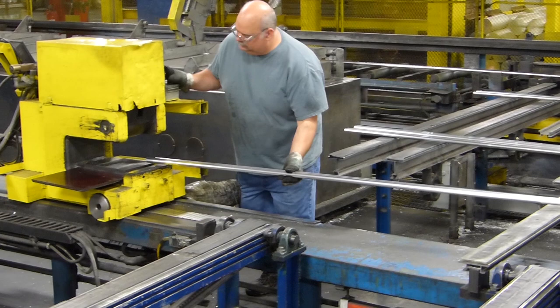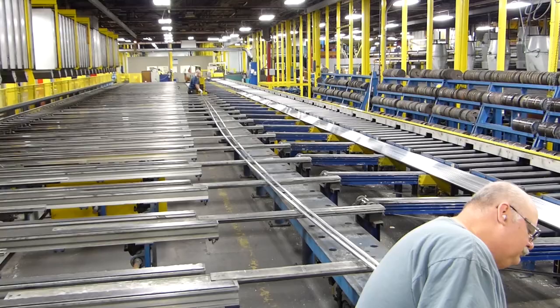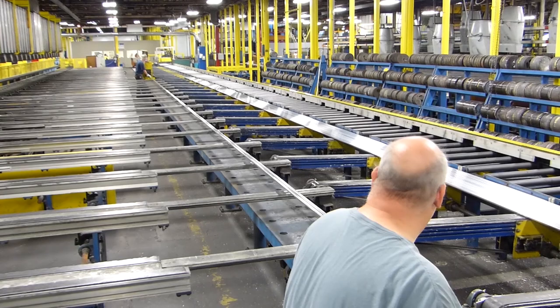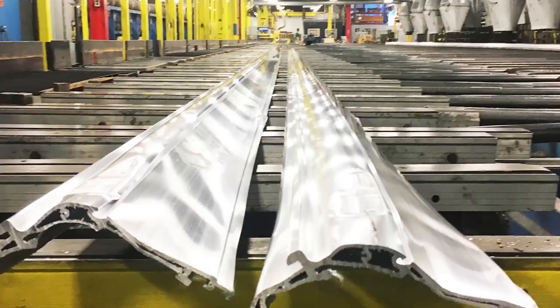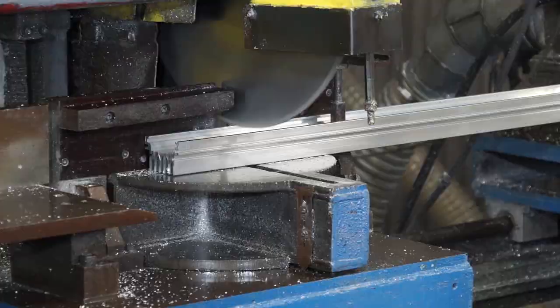This is usually corrected by the stretching process, reducing twist and bow to acceptable tolerances. The ends of the piece, which were distorted in the stretching process, are removed during secondary trimming operations.